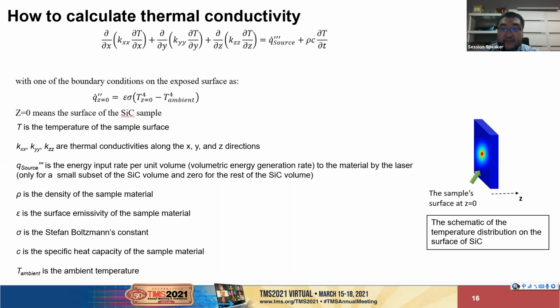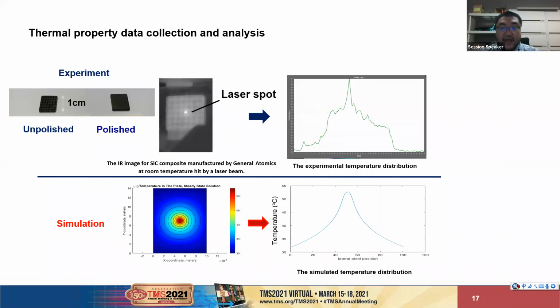The ideal case is you can get the thermal conductivity by inputting all the parameters, but in reality you may not get them all at one time. Still it's okay, because you can get the relative change of the thermal conductivity, and if you calibrate the thermal conductivity in the first place, you are still able to get the thermal conductivity as a function of the radiation. In order to fit the experimental curve, we use the heat transfer equation to get the simulated curve, as you can see in the bottom figures.